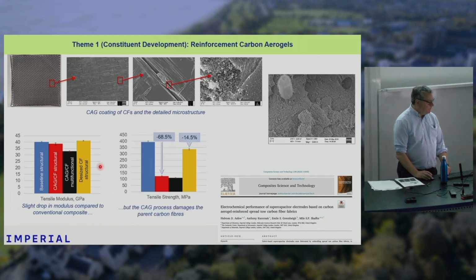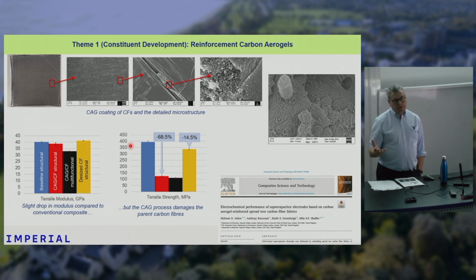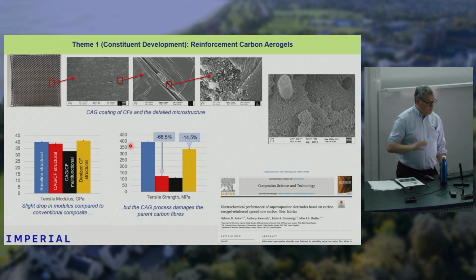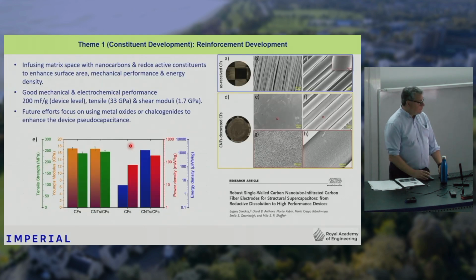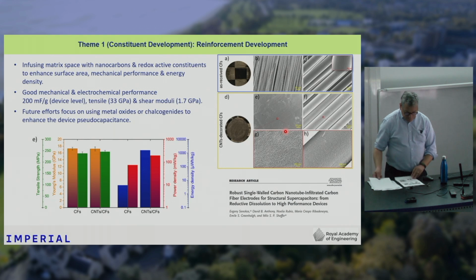However, the problem that we've encountered, and which is what we're addressing at the moment, is that the carbon aerogel process damages the carbon fibers. And so we're now exploring how we can get around that problem. So we do have other strategies for producing electrodes. We're looking at using carbon nanotubes, for instance, putting those onto the carbon fibers as a way of improving the electrode development. So I would say on the structural supercapacitors, the actual electrode development is quite advanced.